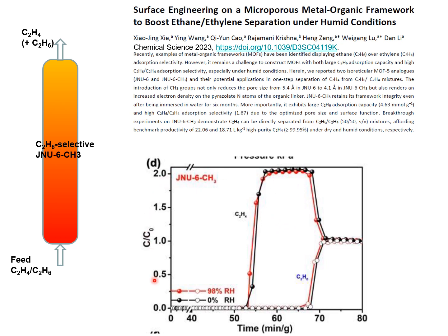Here are the breakthrough experiments for two different feedstocks, one with 98% relative humidity and the other one with 0% relative humidity. The separation performance is uninfluenced by the presence of water.